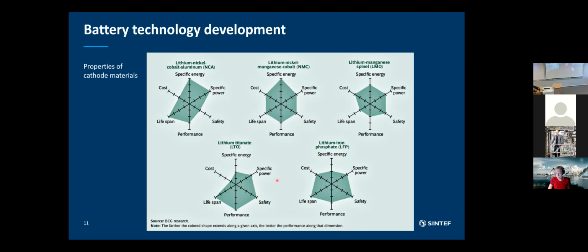And if you look at these 4, you see that none of them really fulfill all the different criteria. If you have high specific energy, you don't have high specific power. If you go for safety, as with LFP, you have to sacrifice some specific energy, maybe also some cost and performance. So at least currently, there's no perfect material. And just to note, this right here, the lithium titanate, is an anode material, but it's an oxide and it's a bit different from the regular graphite. Lithium titanate is used in some specific applications which require higher safety, and I will come back to that a little bit later.